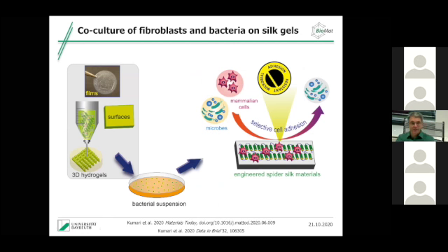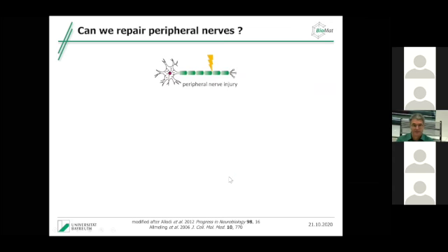What does that mean? Well, with spider silk, especially with the RGD variant, we now have a bioselective material that allows us to selectively grow cells on top and very selectively repel microbes. And right now we are looking at a lot of pathogen-relevant strains, multi-resistant strains, and so far we have not found any bacterium or yeast that can grow on the silk surface. Well, the story continues, but these are very exciting findings for us. And the reason is silk has a nanostructured surface. Remember, this is one physical principle that has been shown also by others that works in microbe repellency. So we can repel microbes just through the nanostructure on the silk surface. And if you want to find out more, this is published in 2 papers, Materials Today and Data in Brief, and they both combine the study that we did over 8 years, as I said.